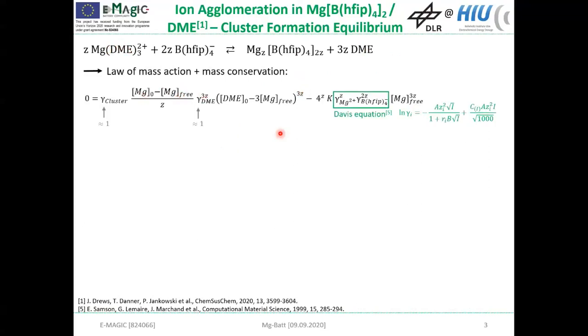And since magnesium is a divalent cation, which means that there are strong electrostatic interactions, and we want to have a look at high electrolyte concentrations, we can't assume that our electrolyte behaves ideally. So for the activity coefficients, we therefore use the Davies equation to describe this non-ideality of the magnesium cation and the following anion.